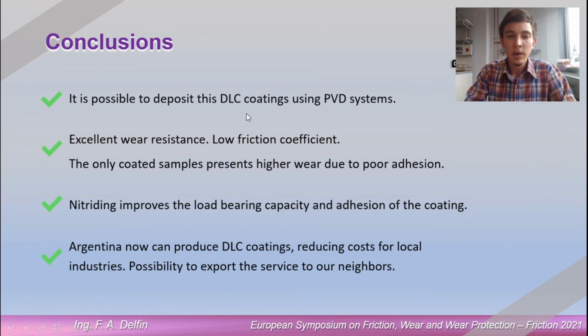We proved we have excellent wear resistance for mechanical applications, and a really low friction coefficient, which is really important for energy saving purposes. But we have this problem with the only coated sample, which presents high wear due to poor adhesion, and the nitriding did help to improve that adhesion, which led to better wear resistance. So we can extend the lifespan of mechanical components using this combination of treatments.